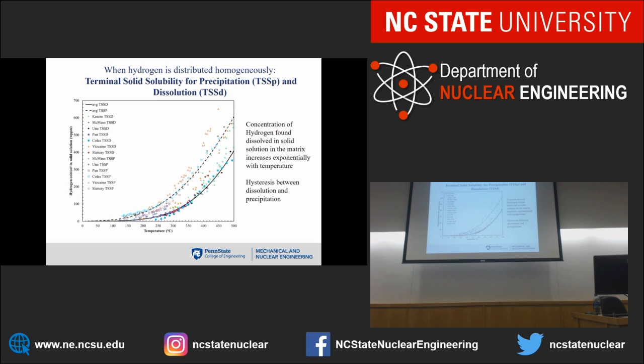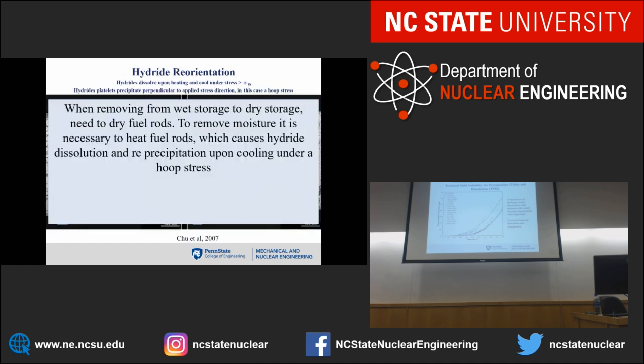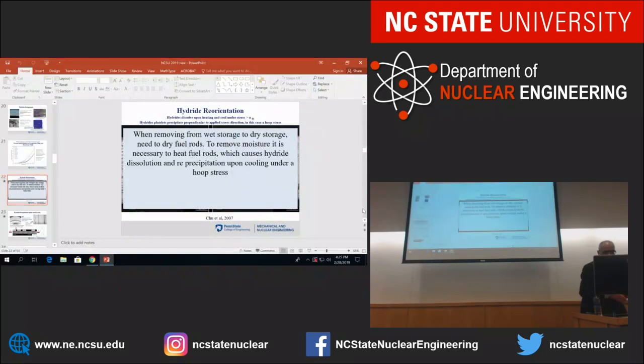There's a hysteresis because it's not easy for the hydrides to nucleate. They'd have plastic deformation associated with them. This hysteresis has always been known. This is what's called the TSSP and this is the TSSD, TSS dissolution and TSS precipitation. And only one of them is a thermodynamic limit. We believe it's the TSSD, not the TSSP, because TSSP is a kinetic limit, and I'm going to show you how and why. I should have put this in an animation, but I didn't, so let me do that right now.